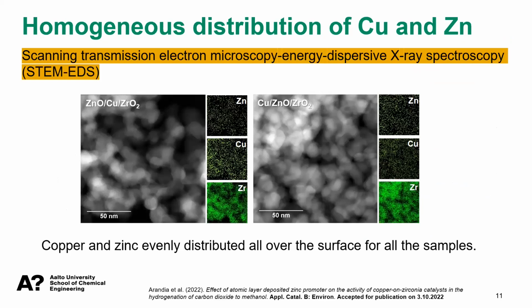We analyzed our samples by different techniques. One of them was scanning transmission electron microscopy plus energy dispersive X-ray spectroscopy, STEM EDS, to check if our metals were evenly distributed on our samples. And actually, I show you here two examples. We observed that both copper and zinc were evenly distributed all over the surface for all the samples. So somehow we succeeded in dispersing our metals all over the surface. That's an important thing.